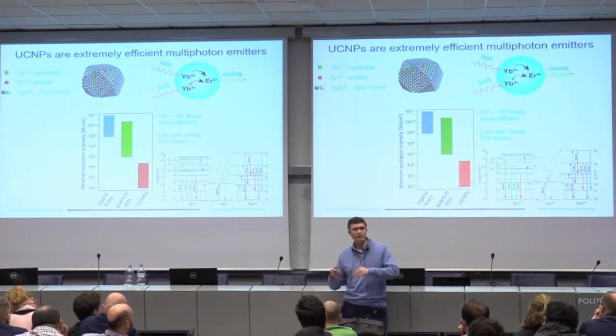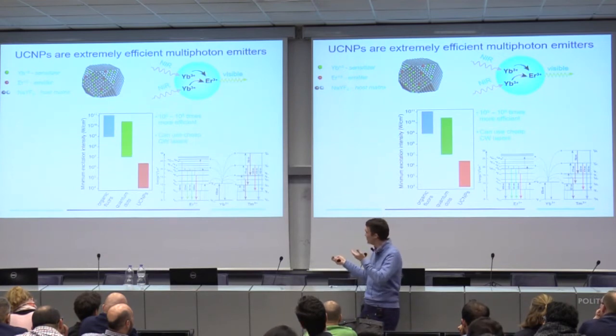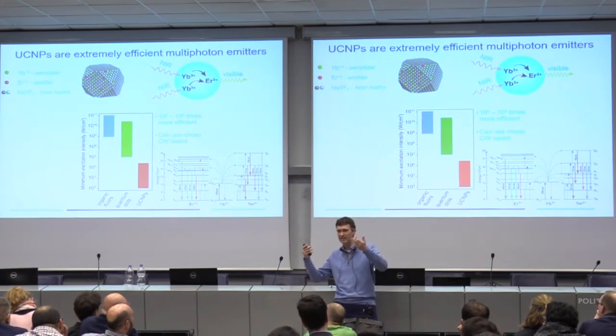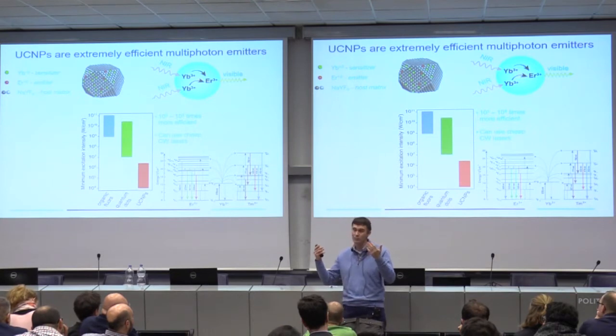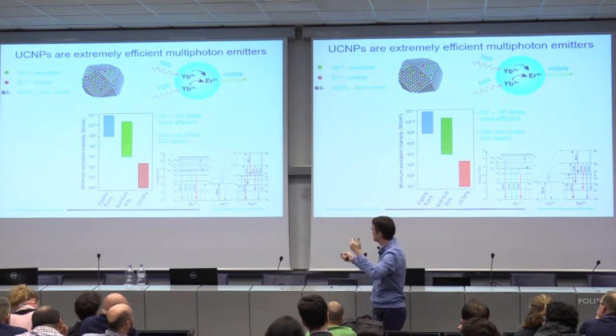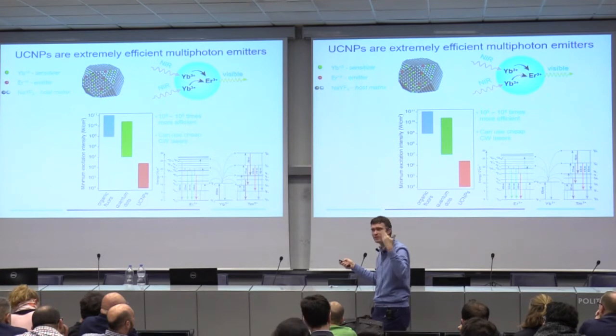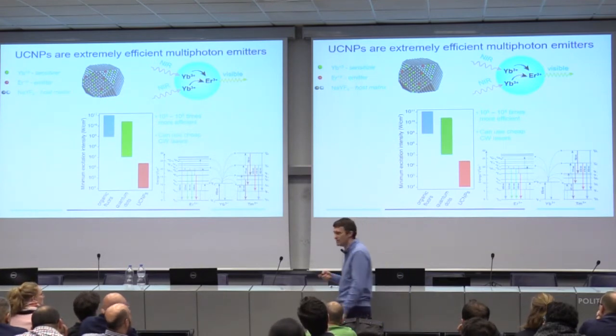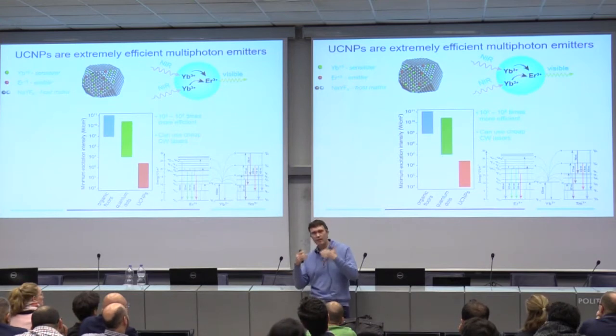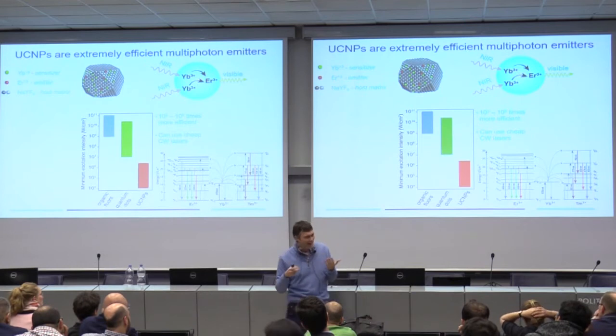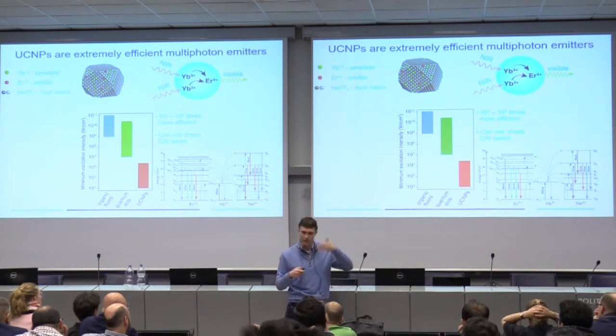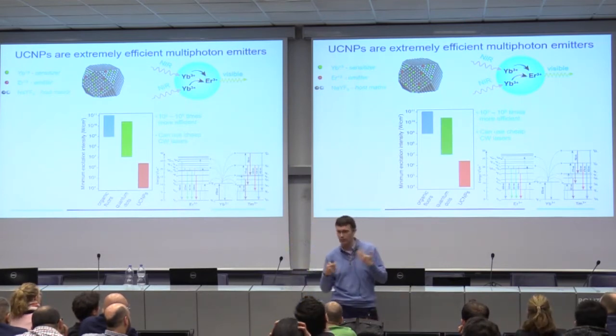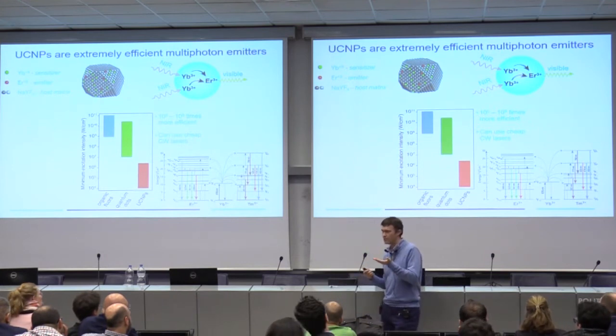Once you get, say, an erbium ion excited to its first excited state, it just hangs out there. It's relatively easy to absorb another photon and go up to another excited state. You just climb up the ladder for every photon that you absorb, and eventually they recombine and emit a higher energy photon. So that's how these work. Because they have real, very stable excited states, it's very efficient at doing this upconversion. It's sequential upconversion, as opposed to the multi-photon absorption that happens in dye molecules. That's why it's so much more efficient.